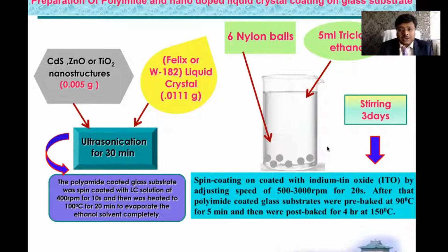Nylon 6 balls are dissolved in trichloroethanol with 3 days of continuous stirring, and a polymer solution will be obtained. You can see we just coat it on the quartz substrate or glass substrate. After that, we can groove it with the rubbing machine, so that with proper grooving, the nanomaterials will be aligned very distinctly and properly. Otherwise, they are just coagulated. You cannot distinguish those nanomaterials just over the quartz substrate or glass substrate.